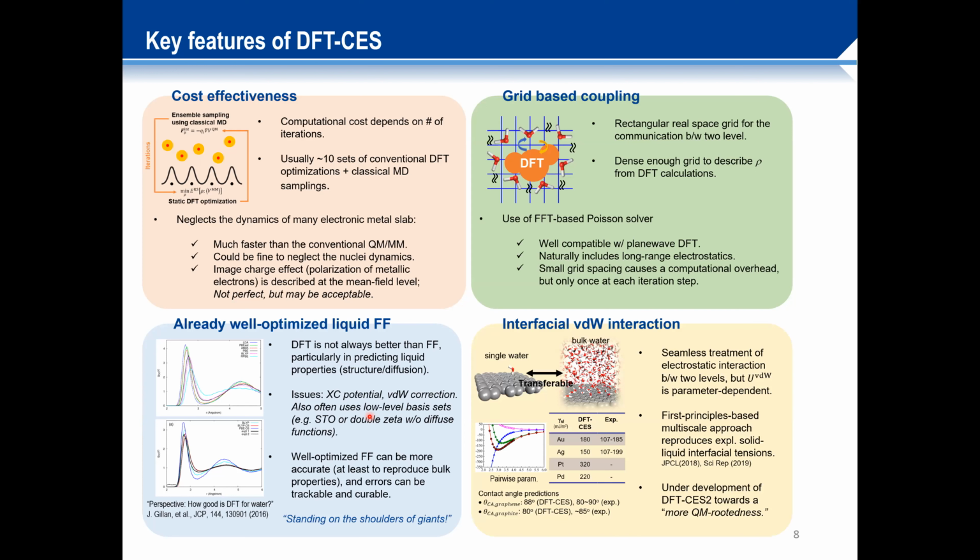The only headache is the interface part, where the electrostatics, using the grid-based coupling, is more or less seamlessly treated. That's going to be fine. But the more complicated part is the interface van der Waals interactions. So throughout previous studies, we developed a way to systematically develop the required van der Waals potential parameters based on first principles calculations.